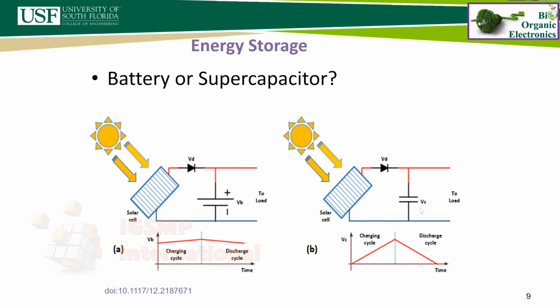In fact, supercapacitors are much better because we are able to charge them from zero almost to the peak voltage. And when we use the charge from them, we can go down to almost 0 volt and consume all the stored energy. Whereas with batteries, we have a very narrow range of voltage for charging. And if the intensity of the light during the day is not sufficient, we cannot technically charge the battery, and